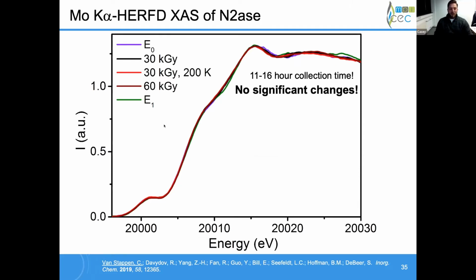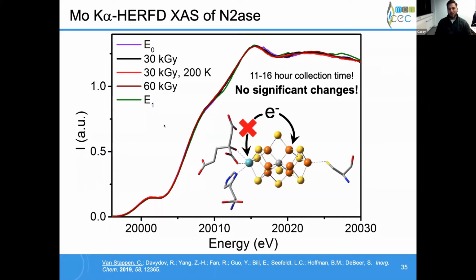I think these are very pretty spectra. They're collected over quite a long time, and we don't observe any significant changes. So this seems to indicate pretty strongly that, counter to what was proposed in this 2019 Mossbauer paper, we really do not have any observable reduction at molybdenum. With that in mind, of course, then we have to have reduction at iron, right?